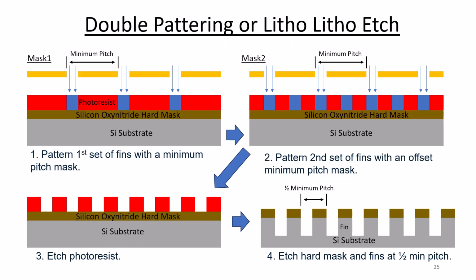So let's talk about double patterning. It's also known as litho-litho-etch. And this just shows a series of steps here. We're going to start off with a silicon substrate with silicon oxynitride hard mask. We're going to apply some photoresist. We're going to bring mask number 1 here, and we're going to expose the photoresist in one area. Then we move over to the second part of this slide, and we bring in mask number 2, and it also has the same minimum pitch as our first mask, but it's slightly offset, and we expose more of the photoresist using mask number 2.